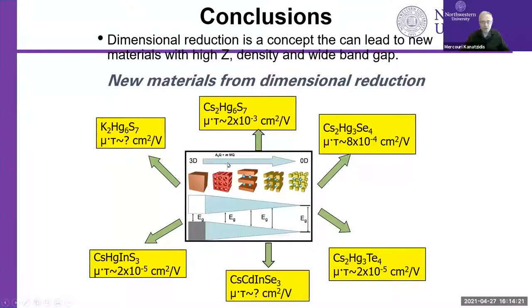And so from the dimensional reduction, here are some promising compounds, and here are the mu tau, mobility-lifetime products. You see here, these are quite good and promising. Some are a little bit low, 10 to the minus 5, so we can reject them, but others are 10 to the minus 4, that's good enough to do further work. And this one is high, 10 to the minus 3. So it's a productive and useful concept.